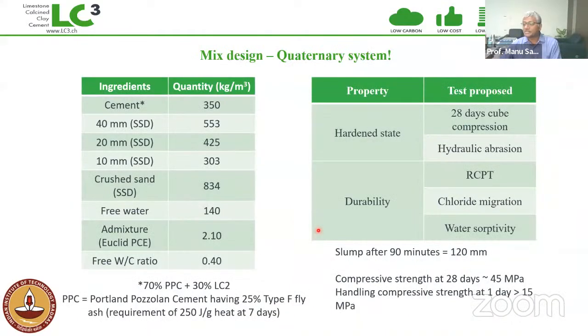So in this case, we used LC2, which is a combination of limestone and calcined clay. And here, the cement which was being used was actually a Portland pozzolan cement, because they had some issues with overall heat of hydration. And because of that, PPC was being used on this site. So in fact, here, our cement combination is cement, fly ash, limestone, calcined clay. It's actually a quaternary combination. We have 4 different types of cementing materials present inside. 350 kilograms of cement and free water of 140, which leads to a 0.4 free water to cement ratio.